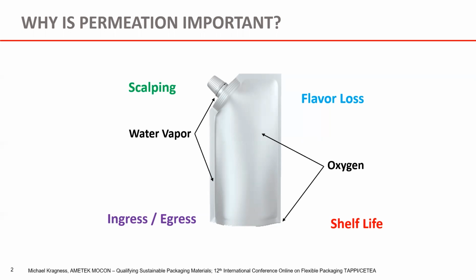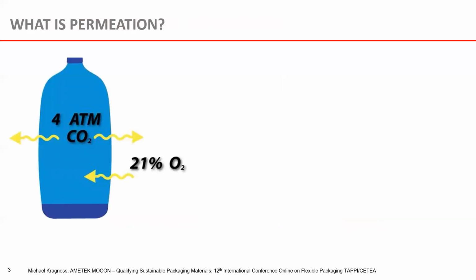So you have oxygen trying to get in, because there's more oxygen in the atmosphere than there is in the product. And since this is a liquid, you would have a high humidified environment inside of the pouch. And since the relative humidity inside of the pouch and the partial pressure of that moisture is higher than in the environment, you're going to get moisture wanting to leave the pouch. So there's always multiple things going on at the same time. And that's why we have to really verify that we're going to get the shelf life that we propose, because there are a lot of factors that can play a role. So now, what is permeation?